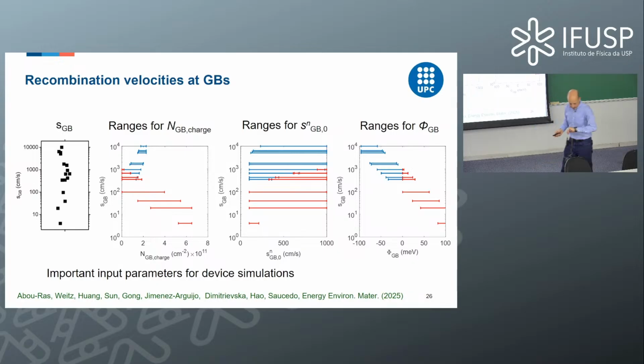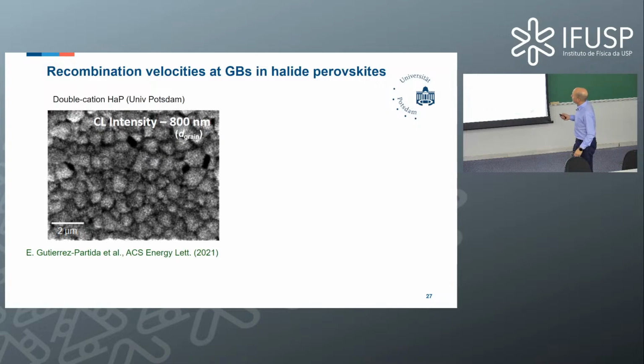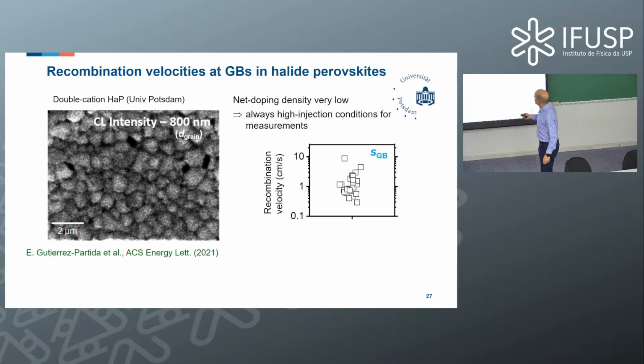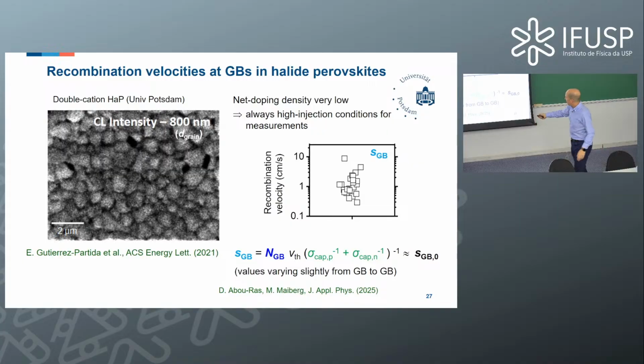So for halide perovskites, we saw that the values were very small. And the range is also confined to roughly two orders of magnitude. This is because in this specific case, the doping density is very, very small. So it's so small that there is absolutely no redistribution of free charge carriers, because there are no free charge carriers for this redistribution, so there is no band bending. And the equation changes to this form.